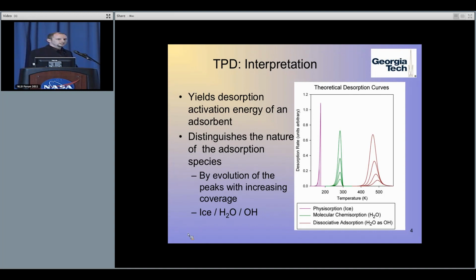The way we can tell these apart in the actual experiments is that the ice, as we increase the amount of water we expose the sample to, will have its peak temperature move to higher temperature. The molecularly chemisorbed water will have its temperature remain the same, and then the hydroxyls that recombinatively desorb as water will actually move to a lower temperature as we increase the initial coverage on the surface. That will be important at the end of the talk.